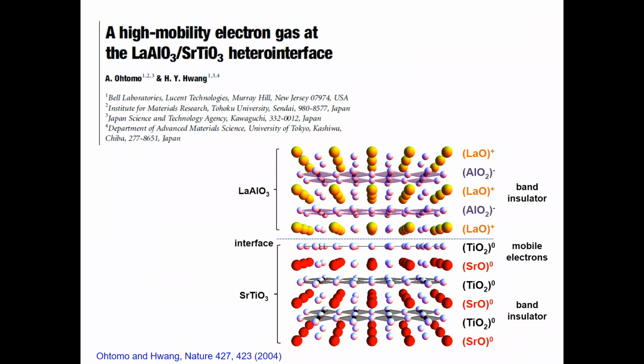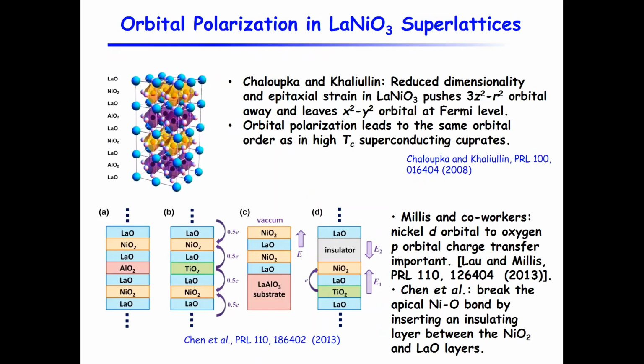And the interface between lanthanum aluminate and strontium titanate is an excellent example of new physics at the interface, where you put two insulators together, and then under certain conditions you find a conducting 2D electron system at the interface. And so that's what Jeremy has been working on. A lot of very interesting work, and also many other groups have been working in this area, made possible by the capability people have to grow these high-quality interfaces.